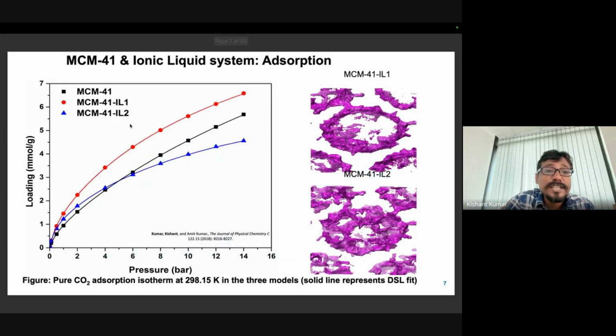Since CO2 adsorption is a surface phenomenon, it's a physisorption process, we can expect a higher loading compared to the pristine. This IL1 is the higher loaded ionic liquid, which has a higher surface area, and MCM41 is also having a lower surface area, but this red one is having the higher surface area at 16 pairs of ionic liquid. So we can see a higher loading because of the higher surface area.